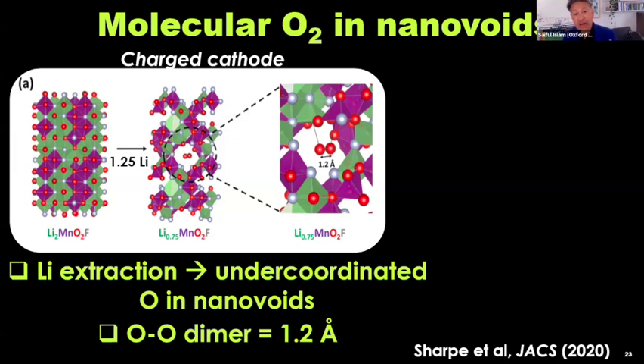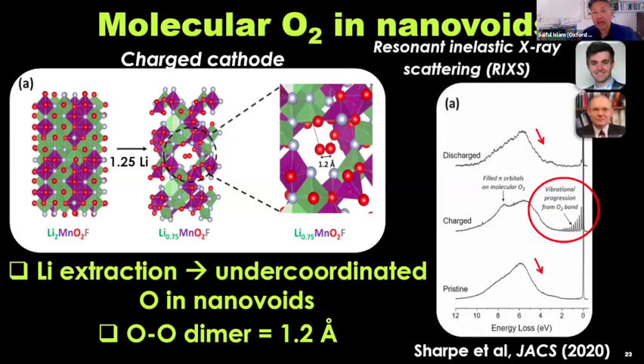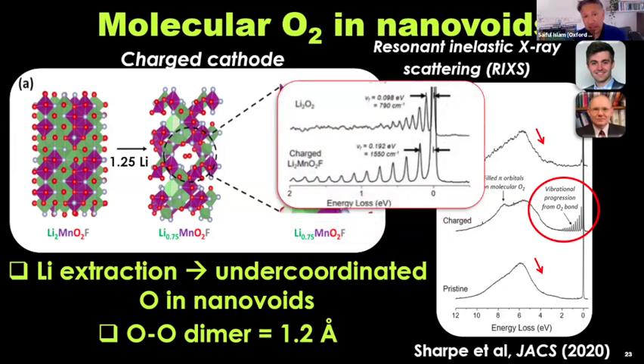Is there any experimental evidence for our simulated prediction? Yes, there is. So this is in collaboration with Peter Bruce and Rob House here in Oxford. They did some resonant inelastic X-ray scattering, RIXS, at Diamond Light Source, and they found that there is evidence for, I'm not an expert on RIXS, but you can see spectra here on the pristine at the bottom, on the charged in the middle, and discharge at the top. For the charge state, there are some peaks and signatures for molecular O2. In fact, you can compare those signatures with lithium peroxide, and they do not tie up. They are signatures for molecular O2 rather than peroxide. So I'm showing you lithium peroxide at the top.